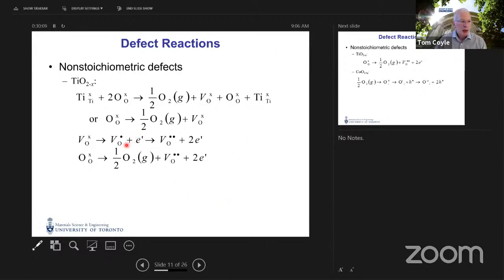And so when we combine this reaction with this reaction, we can write down the net change in the material as being an oxygen on an oxygen site leaving the lattice to form an oxygen molecule and create 2 electrons in the conduction band.